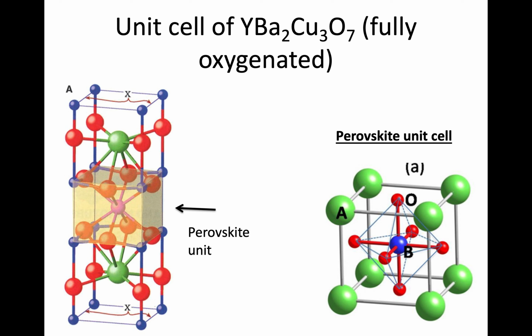This is based on a perovskite structure, as highlighted here, but we have even more cations. You can see we have 3 up here, and they alternate in the different perovskites. You can see one different one here and another here, so you have an even bigger unit cell. It's not cubic anymore because it contains 3 different sub cells, which form the unit cell. But the perovskite is the basis for that much larger, complex structure that you have for this YBCO